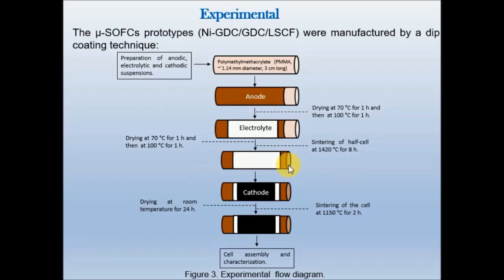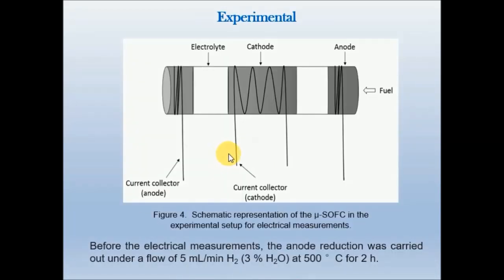During this process, the sacrificial core was decomposed. The cathodic suspension was applied by brush painting and dried at room temperature for 24 hours. A final sintering was performed at 1150 Celsius for 2 hours. Silver wires were wound around the exposed cathodic and anodic parts, and silver paint was applied, thus forming the current collectors. Both sides of the cells were then connected into alumina tubes and a cement sealant was applied. A thermal treatment at 260 and 370 Celsius for 2 hours was carried out. Reduction of anode was performed at 500 Celsius for 2 hours with a flow of 5 milliliters per minute of hydrogen. During this process, the open circuit voltage of the cell was measured.